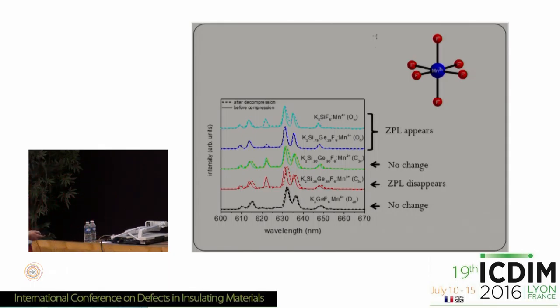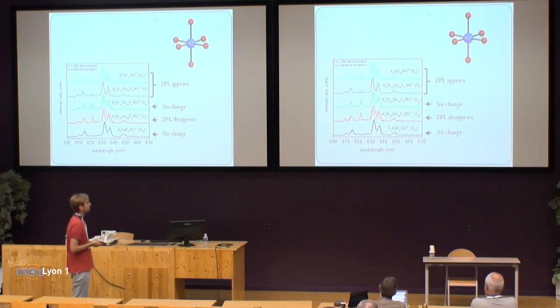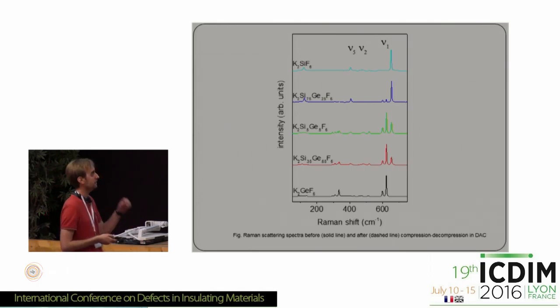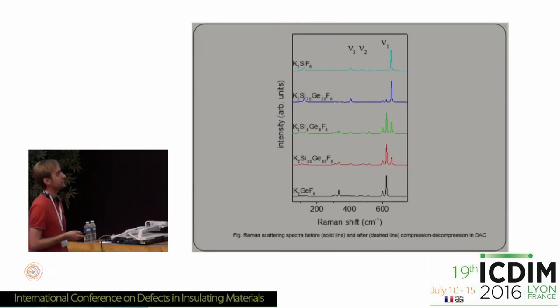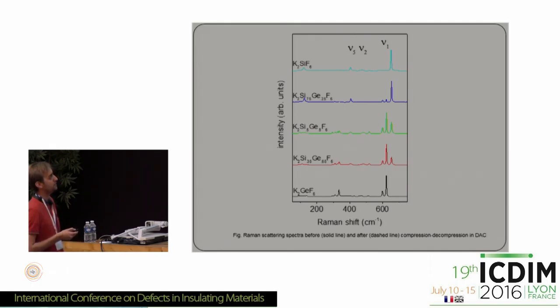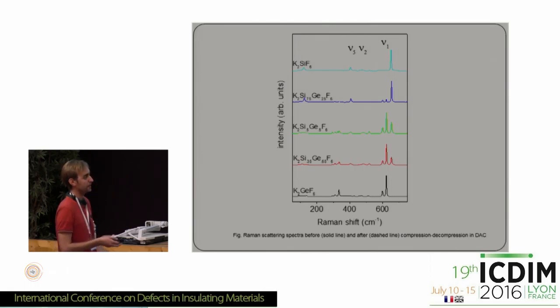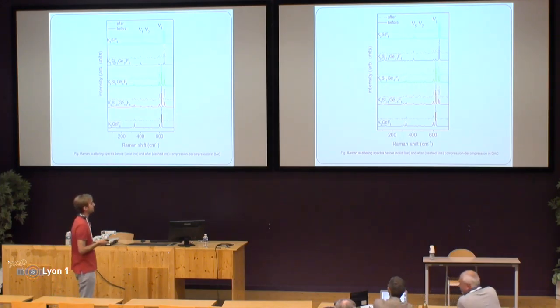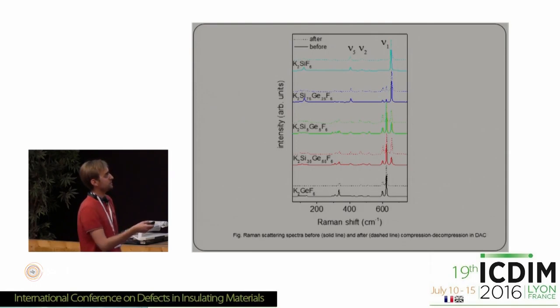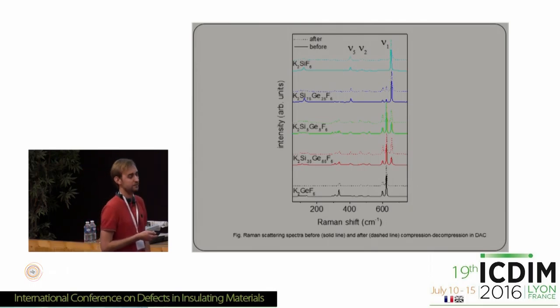This was a strong suggestion of a pressure-induced phase transition. To confirm this, we performed Raman spectroscopy measurements. Looking at the initial Raman spectra of our samples, we focused on the fully symmetric stretching mode of the silicon fluoride octahedra. When we compared the spectra after the compression-decompression cycle, we actually did not see any significant changes.